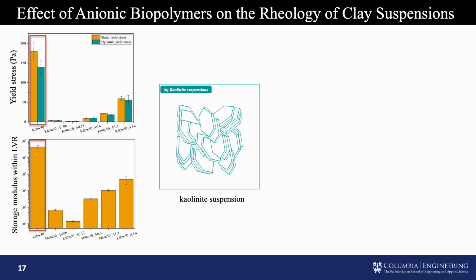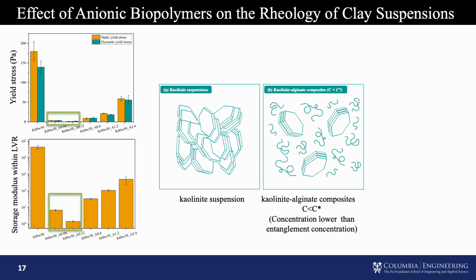When you only have clay in the system, clay naturally flocculates because of the van der Waals force and hydrophobic interaction, which creates some kind of microstructure, right? And if you add a very small amount of anionic polymer, as both this anionic polymer, sodium alginate here, and the kaolinite particles are negatively charged, there will be an electrostatic repulsion force between each other, which will prevent the flocculation of the clay particles.